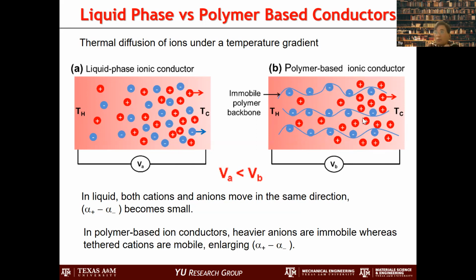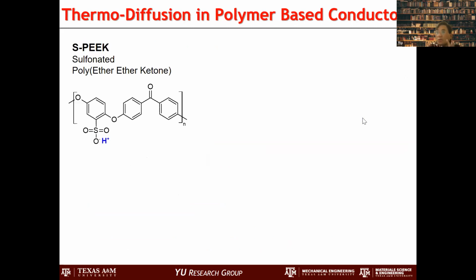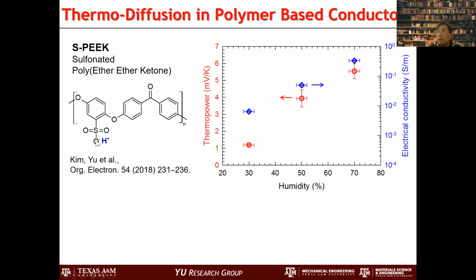And therefore, we focused on polymer-based ion conductors for thermoelectric application, which is what we call polyelectrolytes. So these are all solid state. And we tested many different ones, such as sulfonated PEEK. And here we do have a positive ion, a proton. And it's about 3 to 4, something like that, millivolt per Kelvin, which is good as well.